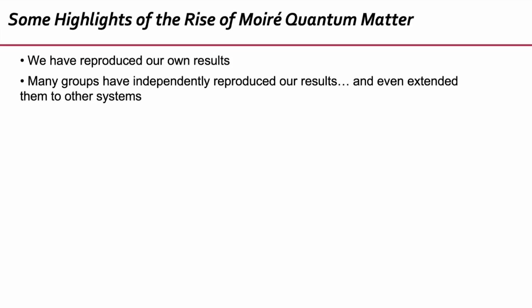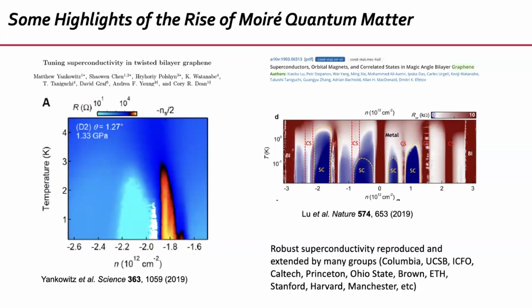So the first groups to reproduce our results were a collaboration between the group of Cory Dean at Columbia and Andrea Young at UC Santa Barbara. They did something very interesting. First they made a magic angle twisted bilayer graphene device, and they saw that it has correlated insulators and superconductors like we did. But then they made a device which was off magic angle, a little bit larger, 1.27 degrees, as you can see here. They measured, and they didn't see any correlated insulators or superconductivity.